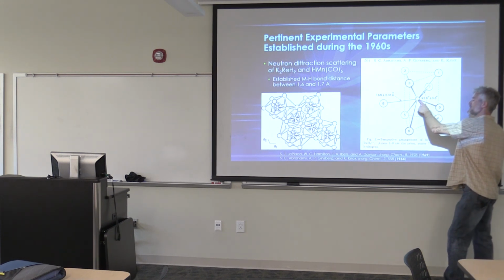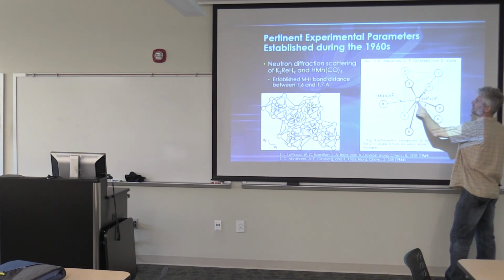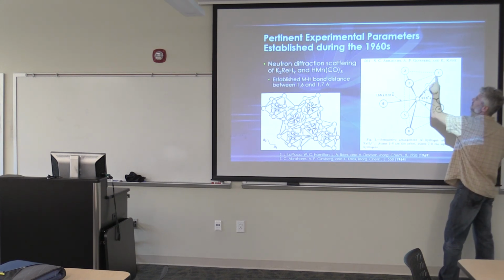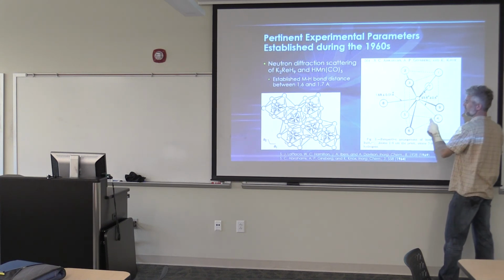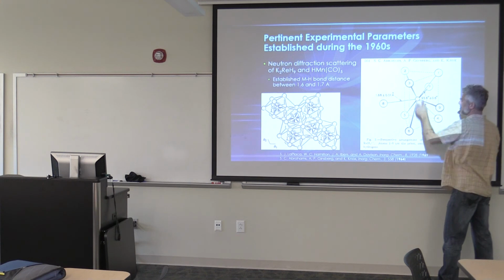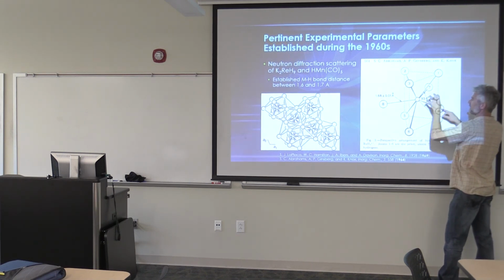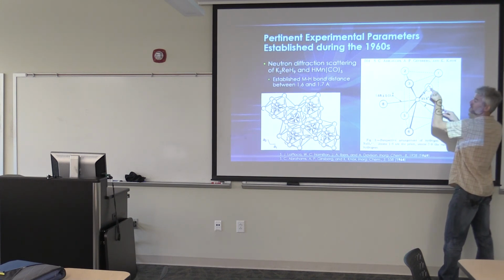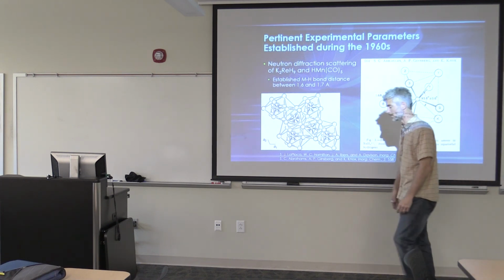They were able to do the neutron diffraction, and so this is our rhenium central metal. And what they found was that the hydrogens, or hydride ligands, formed a trigonal prism. So we have 3 up top, trigonal. We have 3 on the bottom, trigonal. If you connect those, you form a trigonal prism. The other 3 hydrides were embedded into the faces of that trigonal prism. So 1, 2, and then this one on the back side, 3. So it has 9 nearest neighbors.